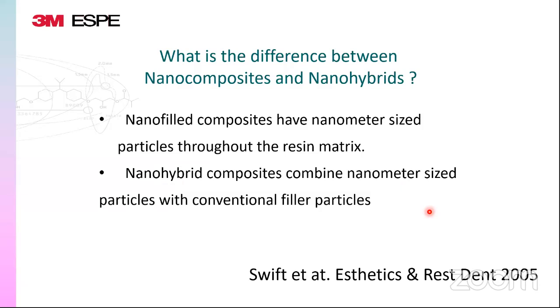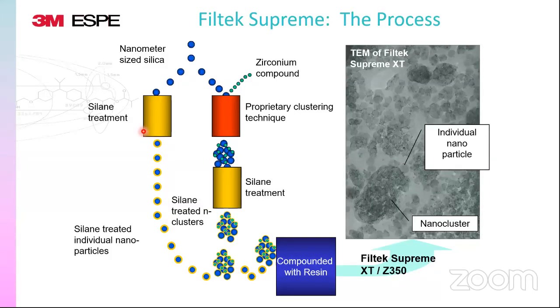But our concern, if you remember, was if I'm going to have 100% nano particles, how am I going to get my strength? So for that, I told you about the sol-gel technique where the nano size particles are silane treated, and these are either clubbed together and then silane treated, or individual particles are silane treated, and then these clusters are put in your resin compound, which gives rise to the nano cluster. Now, let's understand each and every particle in this, whether it be a single particle or a cluster, the individual particle size is 20 nanometers.